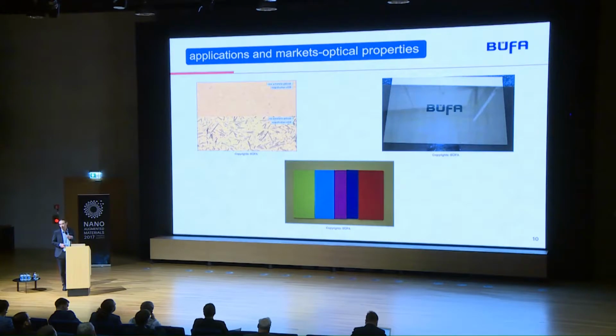This is a gelcoat layer of around 500 microns and has a surface resistivity of 10 to the power 3. So it's really low for the resistivity, and it's still translucent over 4 layers, around 4 millimeters wall thickness of this GRP part.